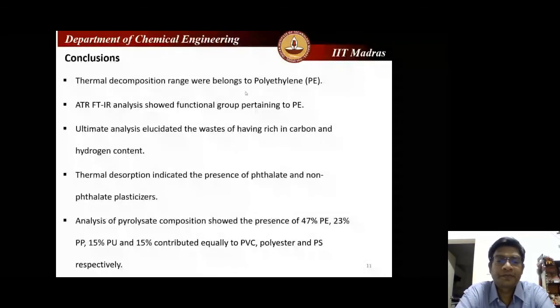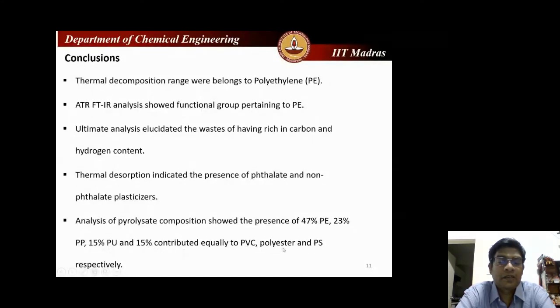And from the matrix of plastic, I got mostly polyolefin plastic. You can see more than 70% is polyolefin, and the rest of the polymers belong to polyurethane, and 15% equal to polyvinyl chloride, polyester, and PS respectively.